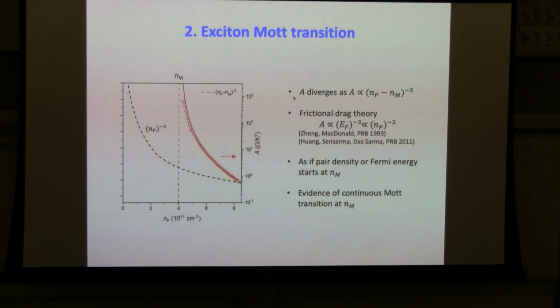So you can see a very big difference compared to this theory which ignores excitonic interaction, compared to the experimental data. The experimental data is as if the pair density just resets. Everything of the density you should just count from the Mott density here. So it suggests that there may be a quantum critical point at the Mott density, that this Mott transition going from excitons to an electron-hole plasma may be quantum critical because of this divergence of the coefficient. But certainly Mott's calculation assumed it was first order.